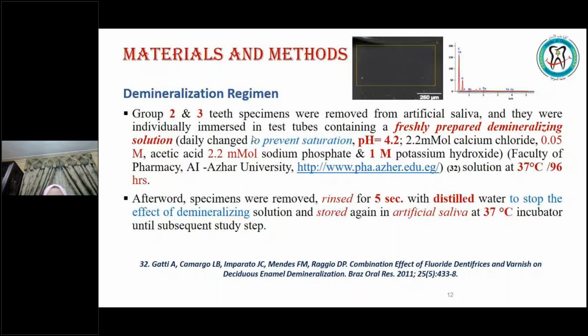The demineralizing solution was prepared at Al-Azhar University, again in Egypt, and it is kept at 37 degrees centigrade for 96 hours. So the demineralization regime was done with the demineralizing solution with a pH of 4.2 at 37 degrees centigrade for 96 hours. Afterward, the specimens were removed, rinsed for 5 seconds, and placed in distilled water to stop the effect of the demineralizing solution, and they were stored again in artificial saliva at 37 degrees centigrade in an incubator until the subsequent study step.